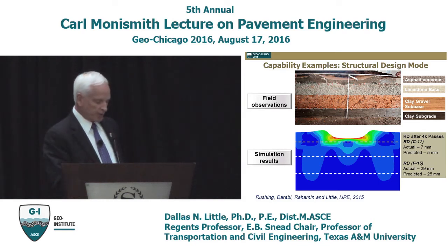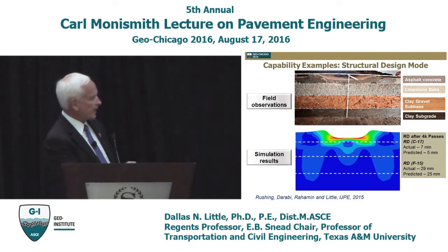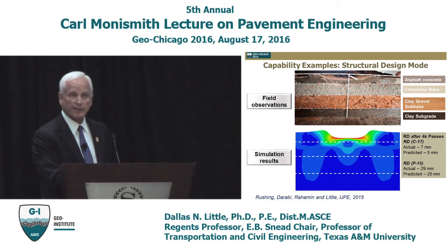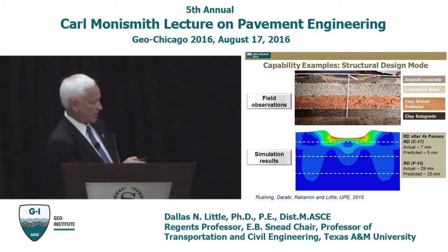And what was interesting to me there was we were able to predict rutting. The asphalt layer was designed to rut. The sublayers, in that case, were considered to be elastic in our analysis. They were very stiff and were not designed to rut. If you look at the cross-section, that's pretty much exactly what happened.